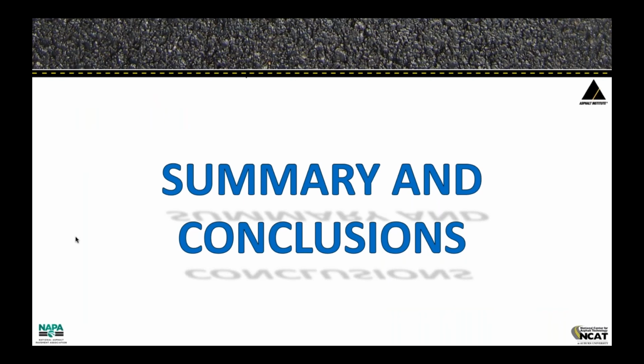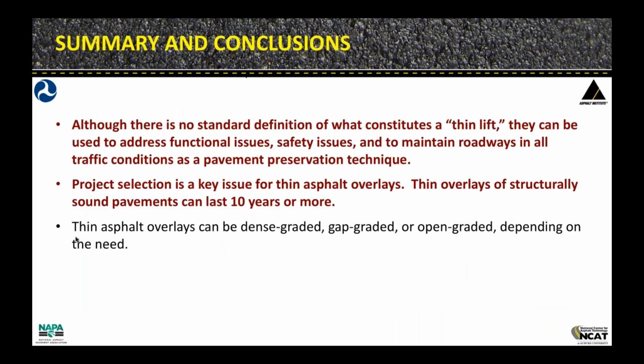So just to try to summarize a little bit, there's no standard definition of what a thin lift is, at least based on the synthesis that was done back in 2014. What they can be used for is to address functional issues, safety issues, and to maintain roadways in all types of traffic conditions as a pavement preservation technique. Project selection, again, is key. And based on the survey results, a number of agencies found that when they placed these thin overlays on structurally sound pavements, they were getting upwards of 10 years of life out of those pavements.